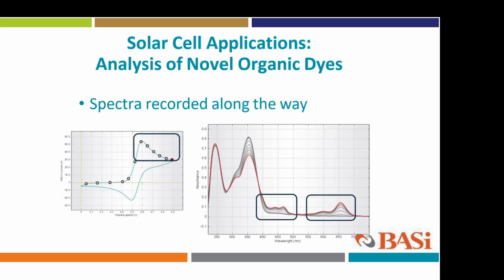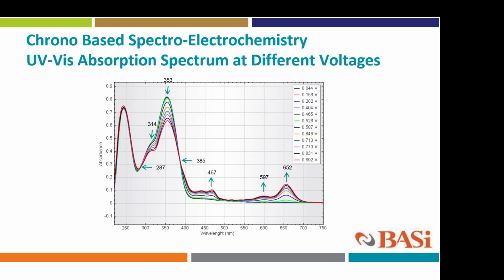So in this particular case, what people generally achieve is they do a chrono-based experiment where they simply understand those voltages, and then they use those voltages and simply hold the potential for 30 seconds and see what happens to the reaction. Obviously, if your reaction is actually emitting light, then it's going to emit those dedicated wavelengths, and those wavelengths add that color change, and you will immediately see how stable your organic dye is.